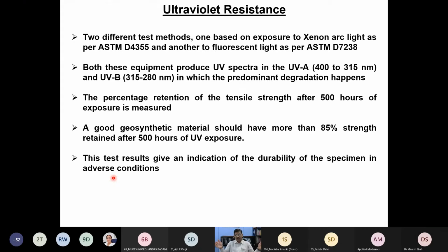If you don't have too much money, you can go for the UV weatherometer, where you subject the polymer to either UVA, where the wavelength region is in the range of 400 to 315, or UVB from 280 to 315. So predominantly, degradation happens in these regions.